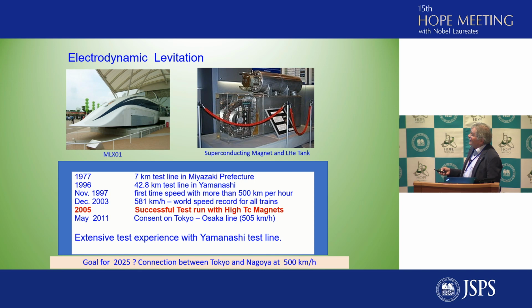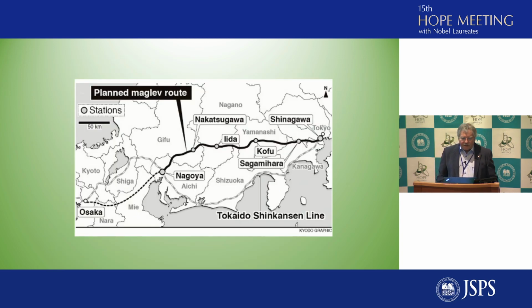This is an example where high-TC superconducting magnets were once tested with such a vehicle. At present, the trains are still using the niobium-based superconductors and helium cooling, but in the long run, one can expect that the train between Tokyo and Osaka, which is still in the planning or also in construction partly, will use the high-TC superconductors. So I think in a few years from now, we will at least have the possibility from Tokyo to Nagoya to use the superconducting high-speed train when we would like to go to Kyoto.